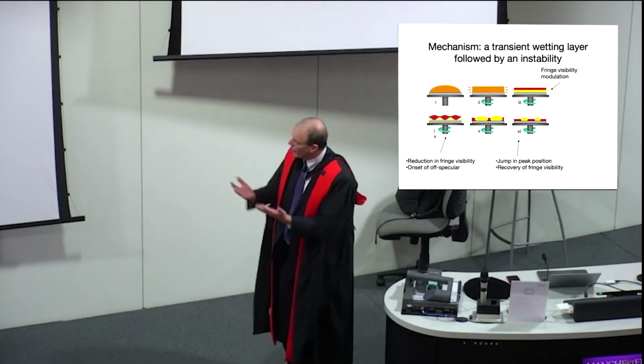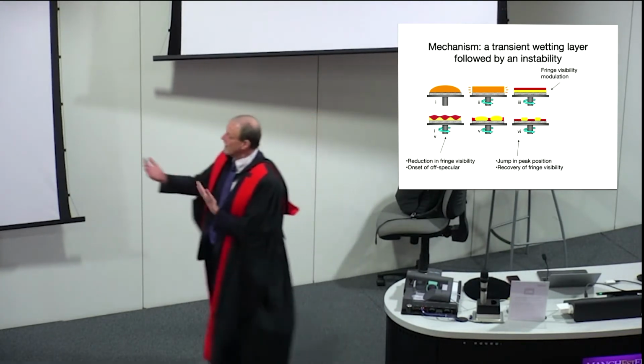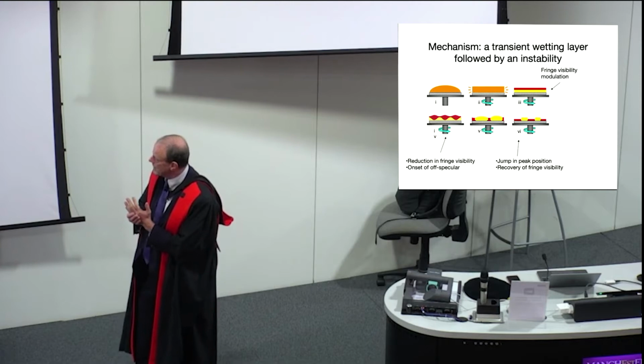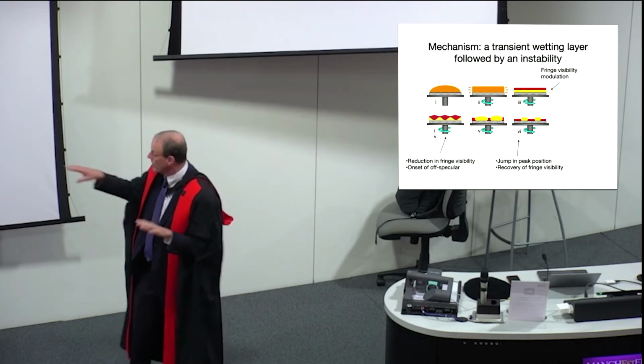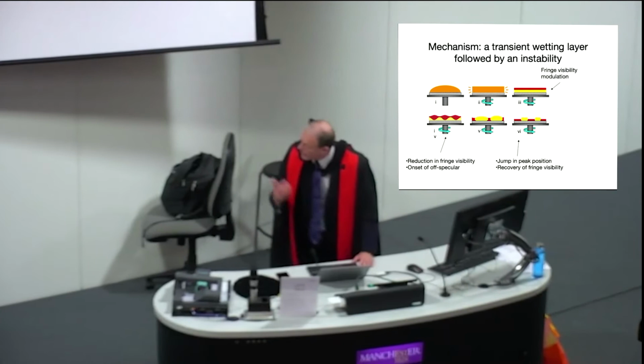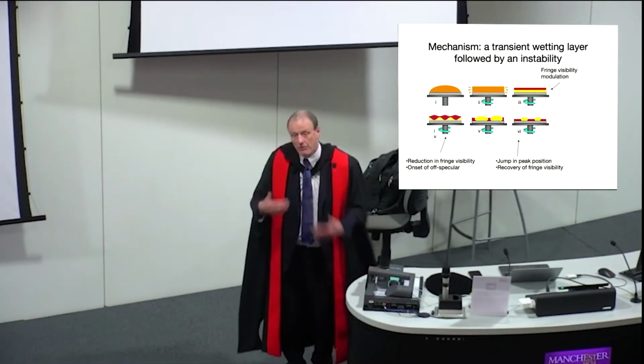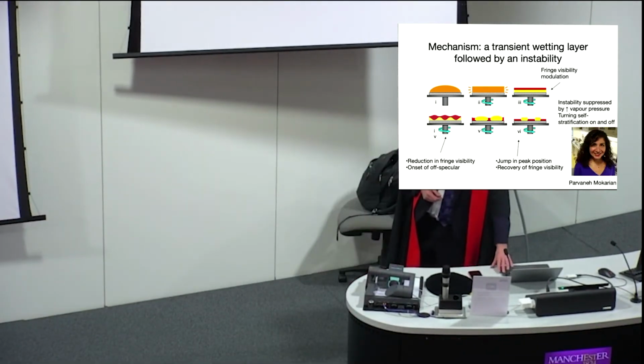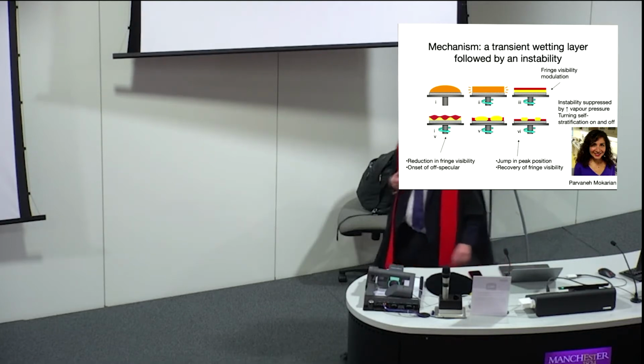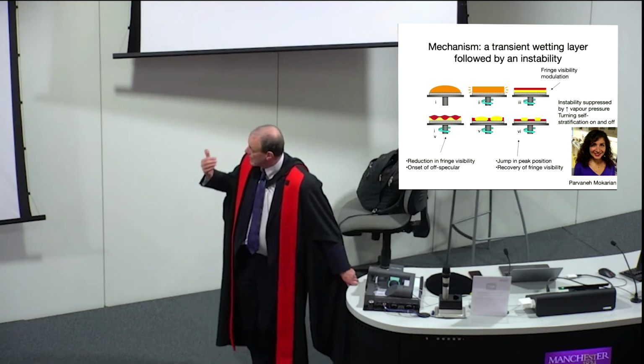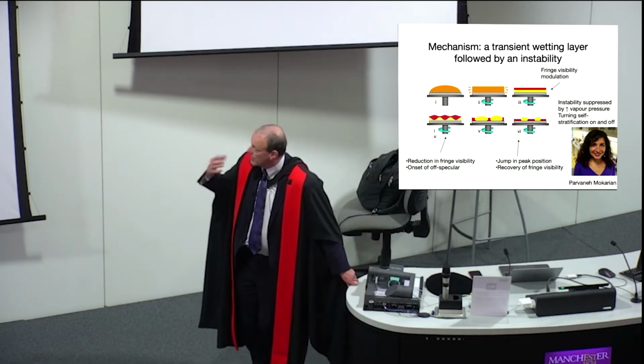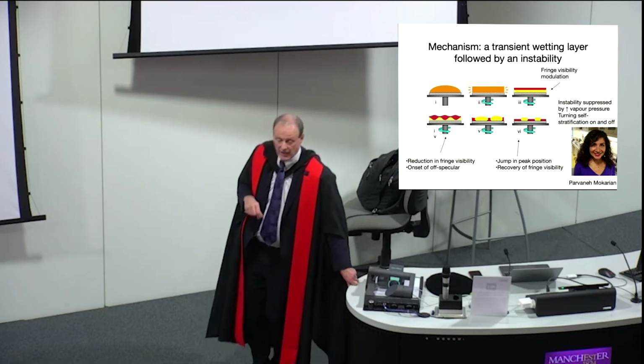What we actually find is that in these systems, they all self-stratify to start with. The question of whether you get a self-stratified film at the end or not is really a question of a secondary instability, where the layers break up and you end up with the phase separated result. Now, if you know the mechanism, you can start to ask: can I modulate this? Can I change the conditions so I can get the structure that I want? Another great student, Parvaneh Mokarian, now in Trinity College Dublin, was able to show that you could suppress this instability, and so you could turn self-stratification off and on.